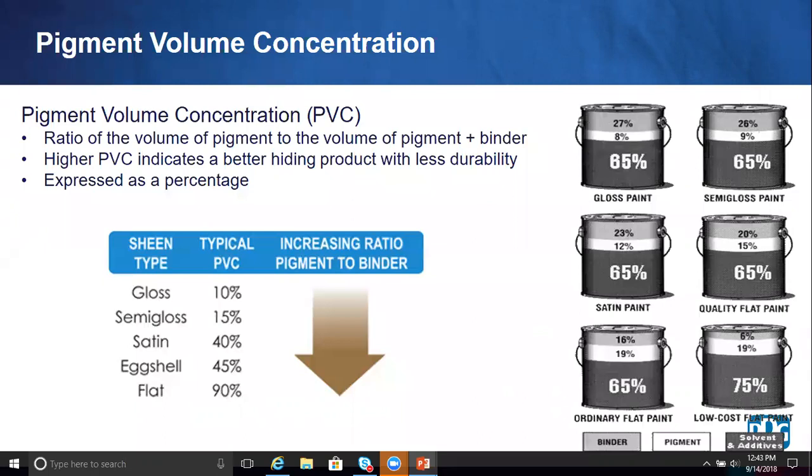When you step into that last can of paint on the right, now you've gone up to 75% solvent. So now 75% of that can of paint is going to evaporate away, leaving only 25% volume solids. And now you've only got 6% binder encapsulating 19% pigment. So that's going to be something that's a very entry-level product, new home construction, a maintenance product, where it's literally not going to be washable at all. It'll touch up great because flat paints scatter light very effectively, to where they don't show any sheen level whatsoever.